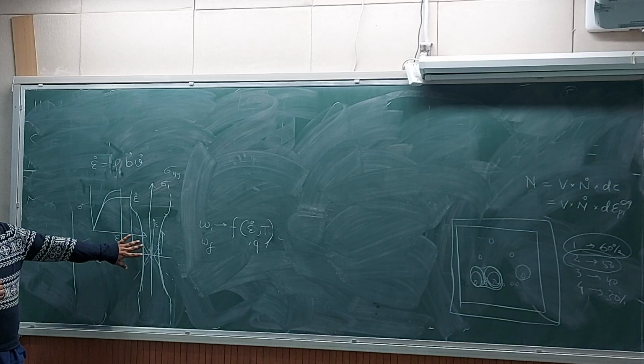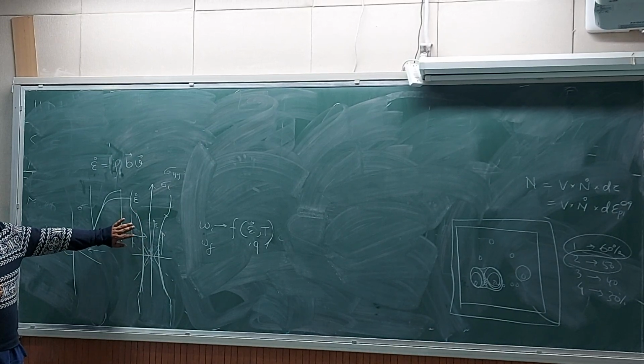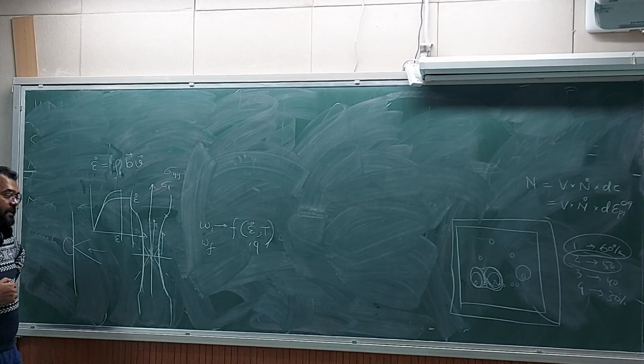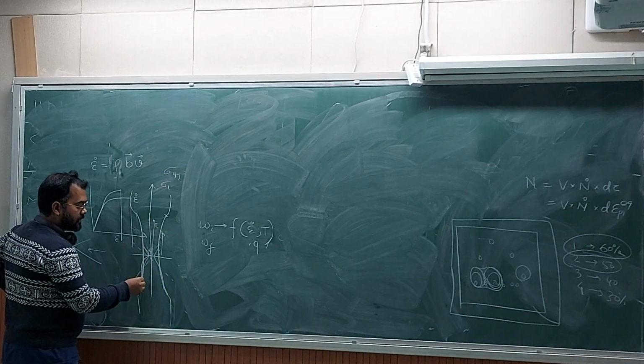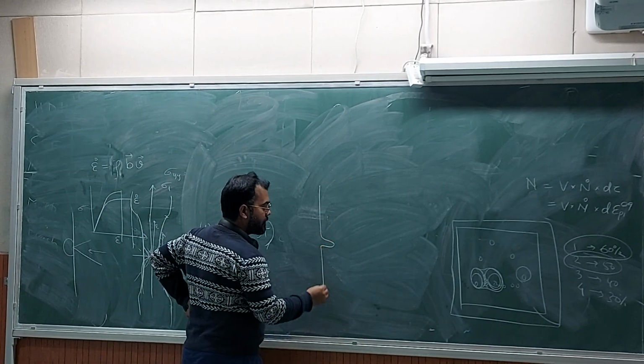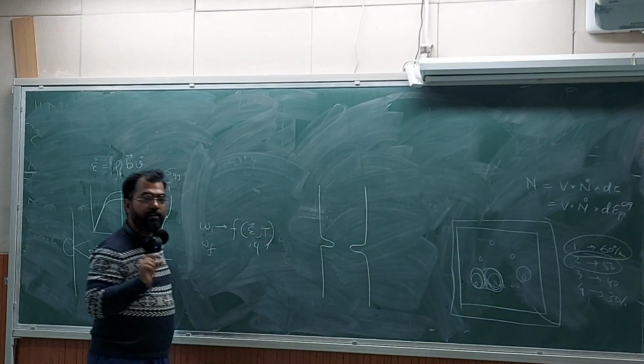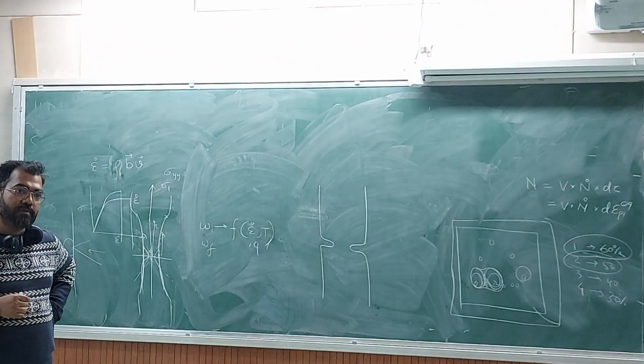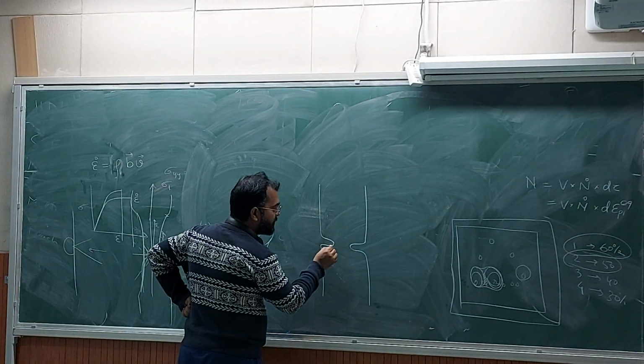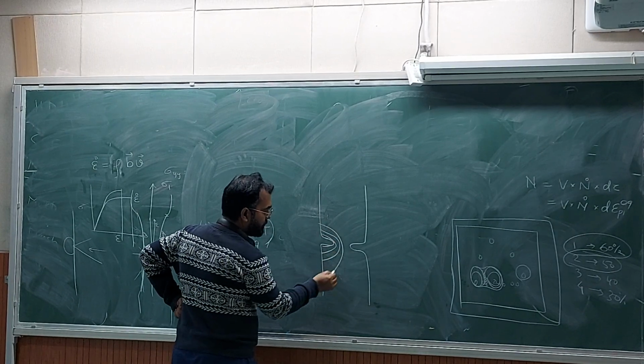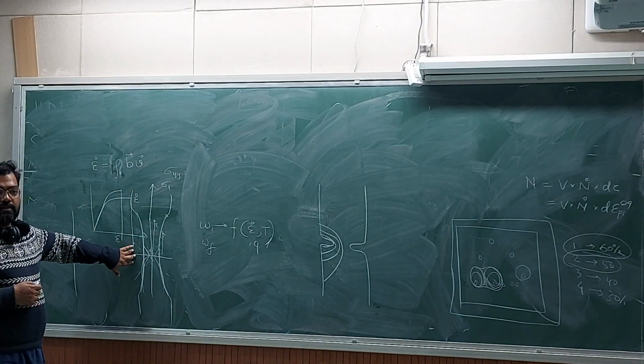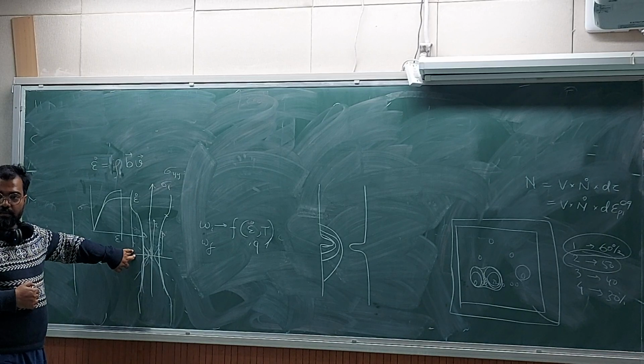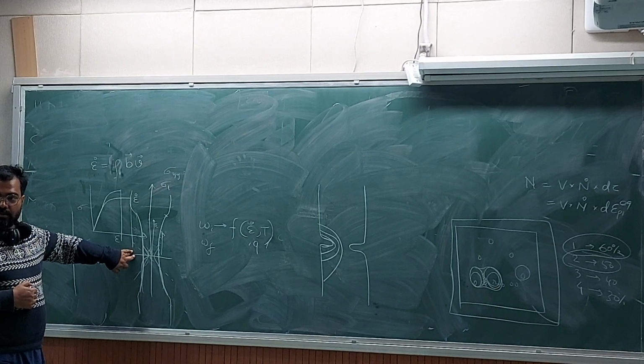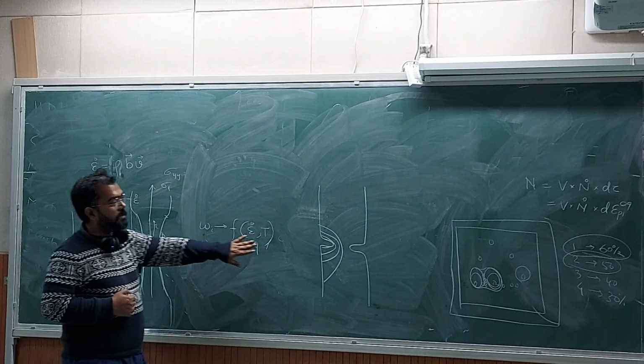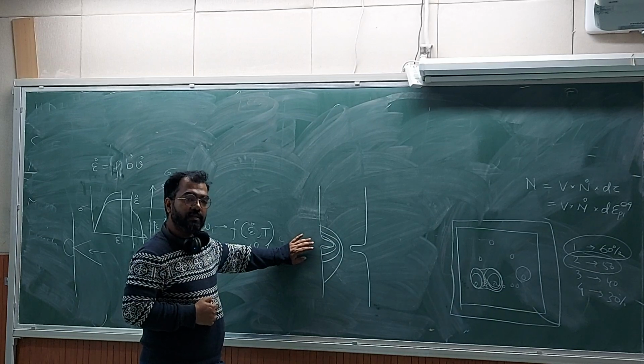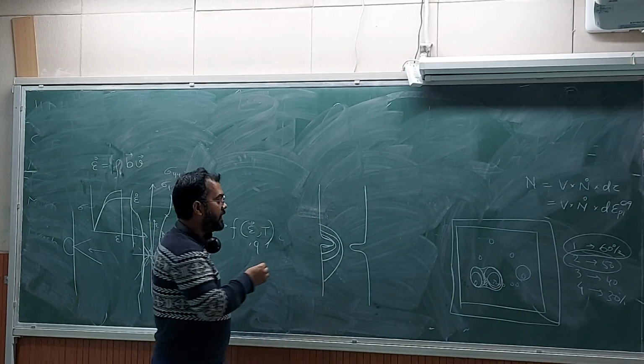But this kinetics, whatever variation you get, will change if you change the constraint. Okay. And in order to check that, you make different types of tensile sample. So you make notched tensile sample. Okay. And you make notches of different radius, because this tensile sample has a notch radius of infinity, isn't it? So then I gradually go to different values of notch tip root radius, and those will create a constant constraint in this area.